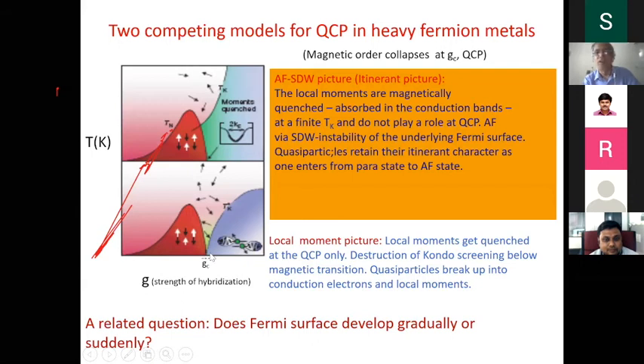There are a lot of controversies on that, and we have done a lot of work to establish one system, which I will not have time to discuss, through collaboration with a collaborator at MIT, using a very powerful spectroscopic technique at low temperature. It shows that it is indeed possible that this interaction, which is responsible for killing magnetism, can in principle survive even in this region also. You may say there is a contradiction: on the one hand I am saying there is magnetism here, on the other hand the Kondo interaction survives. These are all very complex concepts to imagine.